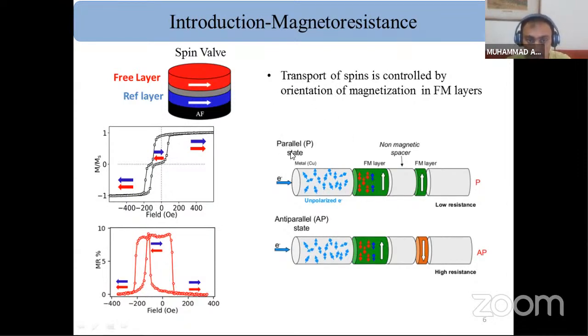Here you can see a parallel state, when the orientation of magnetization in the free layer is parallel with the orientation of magnetization in the reference layer. The reference layer magnetization is upward, and the free layer magnetization is also upward. You see a low resistance and a lot of polarized current passes through the spin valve. Similarly, for the high resistance state, when the magnetizations in the free layer and reference layer are anti-parallel, the spin valve has a high resistance and little polarized current passes through it.